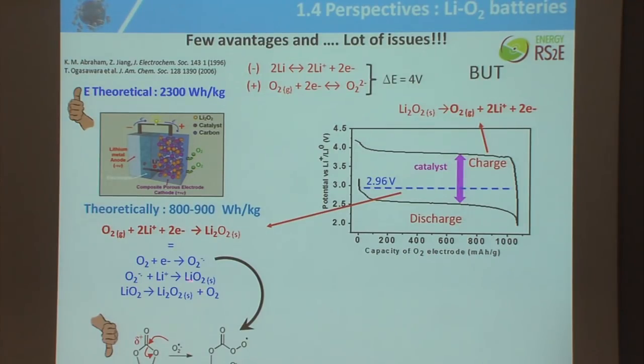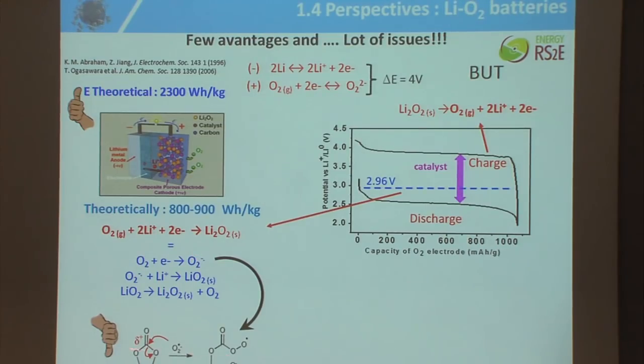You go through this intermediate, which is superoxide ion. Superoxide is the species which is responsible for the aging of a human body. This is a superoxidizing agent. So as long as you form superoxide, you are going to oxidize the electrolyte, you are going to oxidize the carbon, you are going to oxidize everything. So the key problem to solve for lithium-air battery is to trap this superoxide species, which is a reaction intermediate